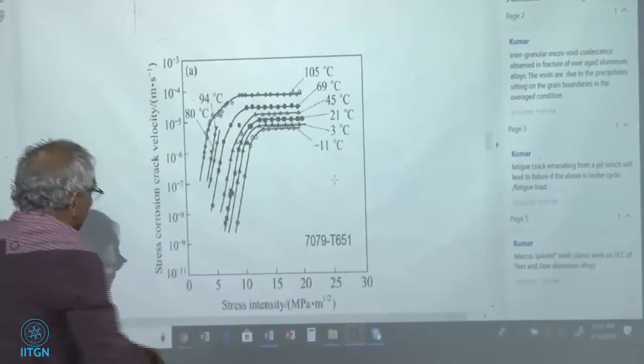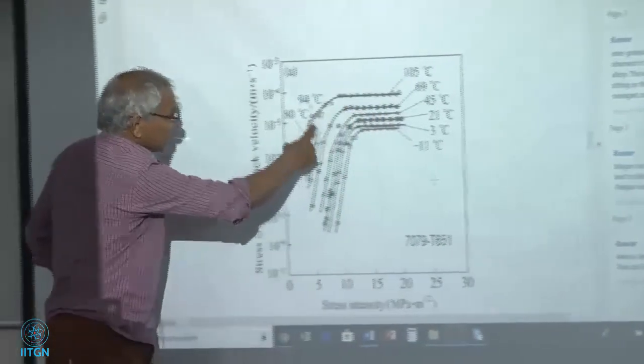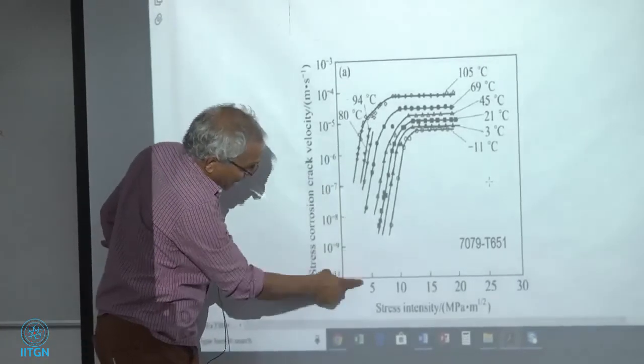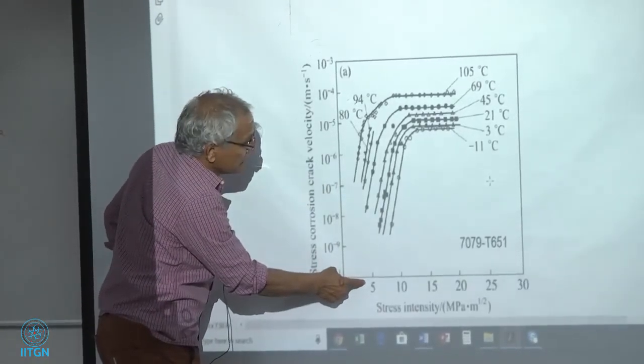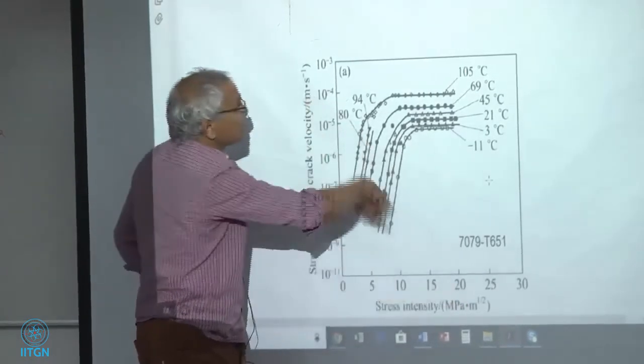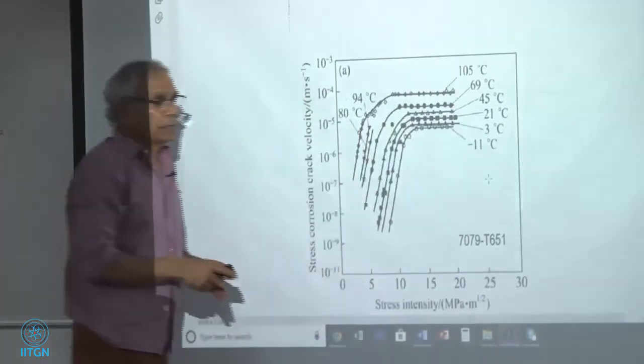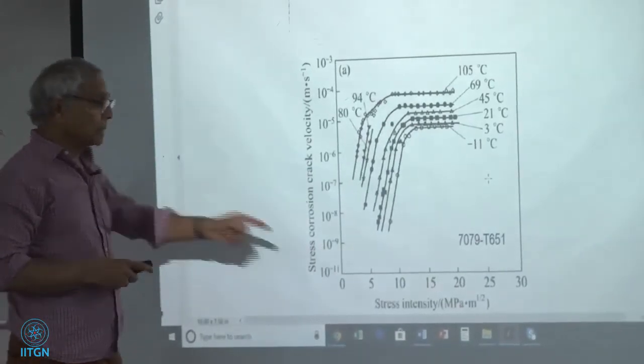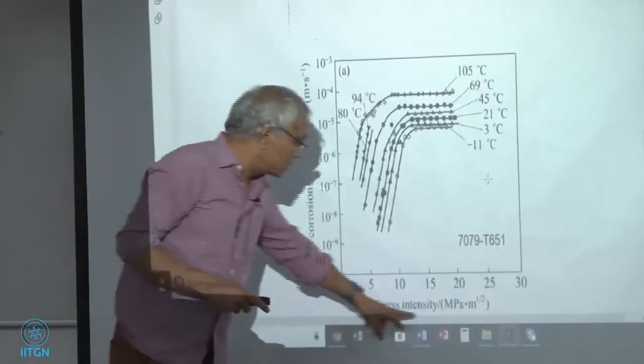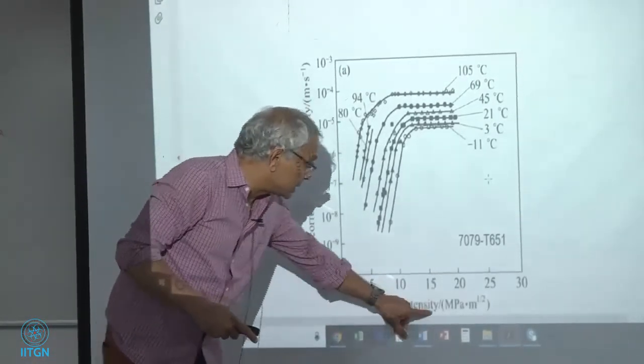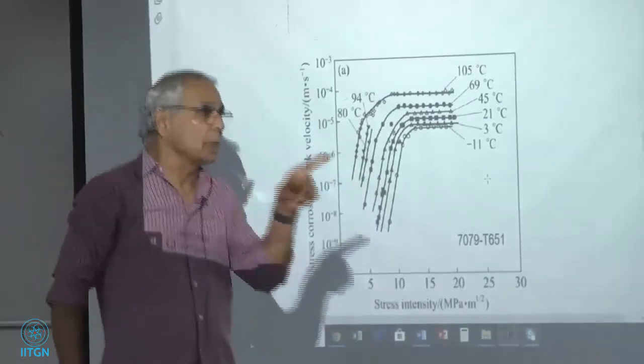They don't use this anymore in the aircraft, but they used to use this at one time. K1, this is K1 SCC. When you say K1 SCC, that's a threshold, right? So these are all K1 SCC, like at 105 degrees Celsius, this is the K1 SCC, this value. But this is stress intensity K at 105 degrees. It's not fatigue, it's just a stress intensity. If it's fatigue, it will be stress intensity range. That's what you have to look for, the word. Range would mean fatigue. If there's no range, it is single.